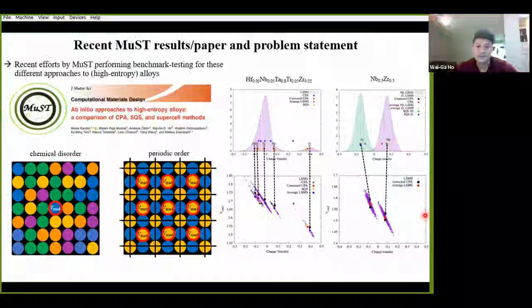And then something to add, however, is that with these QV relationships, the paper also showed it was possible to reincorporate some species-dependent corrections into CPA, and then have this new corrected CPA perform a bit more accurately, which we can get a sense of by looking at how these red corrected CPA dots compare with the blue LSMS averages.